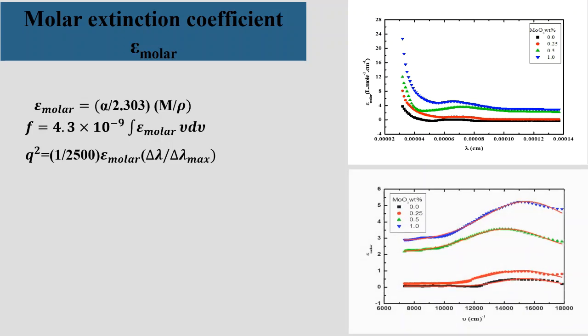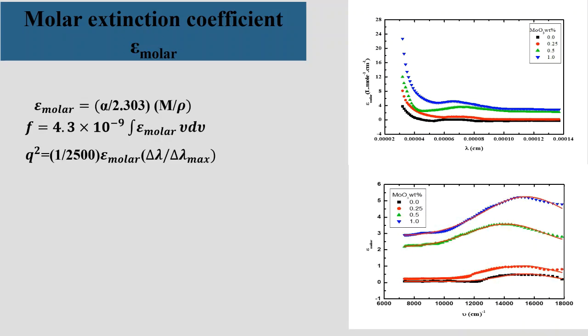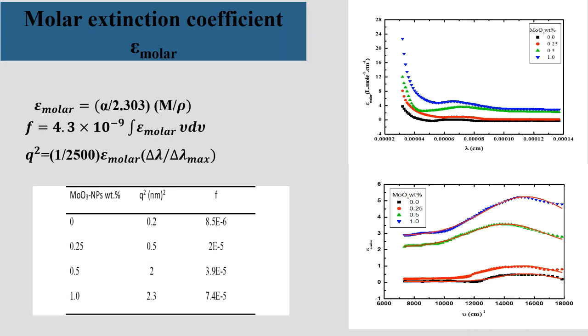And from Gaussian fitting, which is with the red line for the molar extinction coefficient, we calculate the electric dipole strength Q square and the oscillator strength F, and we observed that the electric dipole strength was increased by increasing the molybdenum trioxide nanoparticle.